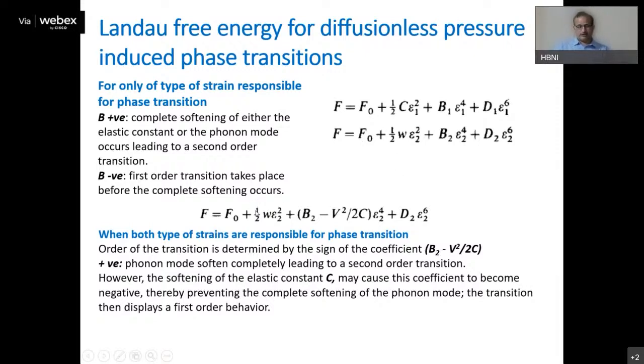Whereas in case when you have both homogeneous strain and shuffle strain, you have this kind of free energy. Here, if this expression is positive, considering that there is no evolution of this term with respect to the pressure, then the phonon mode corresponding to shuffle has to soften in order to give rise to this phase transition. But as you increase pressure, this elastic constant, basically this modulus, can also soften. And as soon as it softens, this term can become negative. In that case, even before the phonon mode softens, there is a possibility of getting this phase transition. And this will be mainly a first order kind of phase transition.